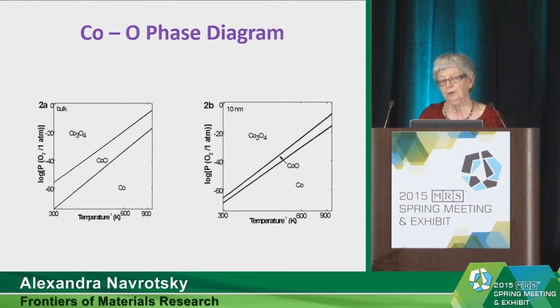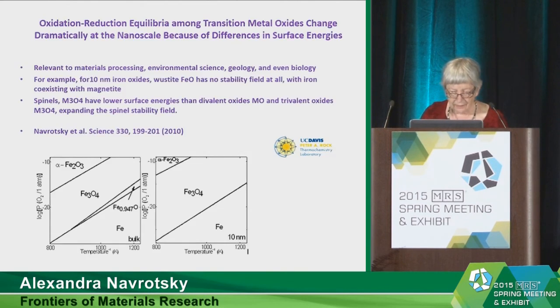Similarly, if you look at the reduction of oxides in the electron microscope, the redox equilibrium may shift. What happens under the electron beam and what happens at the low fO2 that you're looking at in a high vacuum, you have to worry that your nanoparticles will be reduced differently from your bulk particles, and differently not just because of kinetics, but because of thermodynamics.